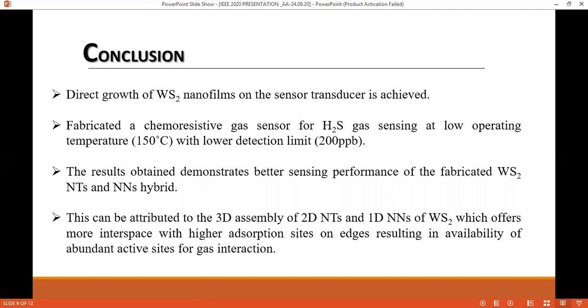This is attributed to the 3D assembly of two-dimensional nanotriangles and one-dimensional nanoneedles of tungsten disulfide, which offers more interspace with higher adsorption sites on edges, resulting in availability of abundant active sites for gas interaction. Moreover, multi-layer nanofilms offer more electron transfer channels for improved reaction between the material and target gas.